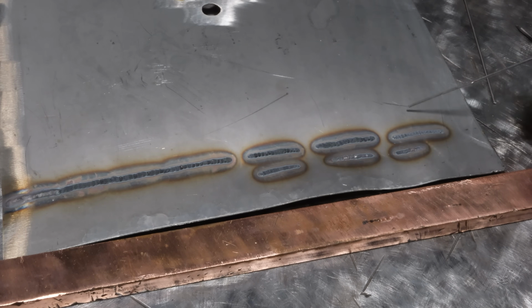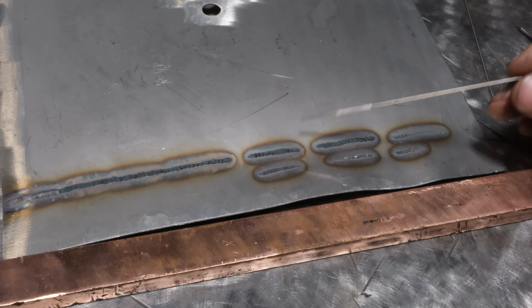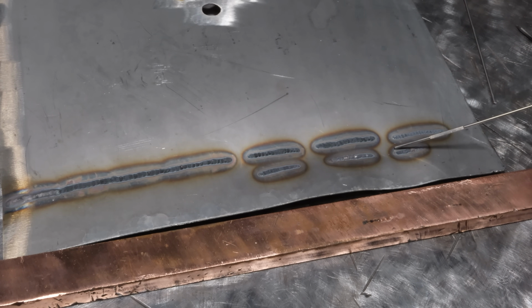Even where I tried to clamp this to this copper bar, because it wasn't in full contact with it, which is typical on thin material, it's going to warp and pull off of it. Even that has pretty significant oxide. The copper bar or backing bar, quench bar, whatever you call it, typically works better on outside corner joints and things on thicker material. On thin stuff like this, it can be an uphill battle to get adequate contact to where it works. So the question is, this oxide layer, is it a defect?